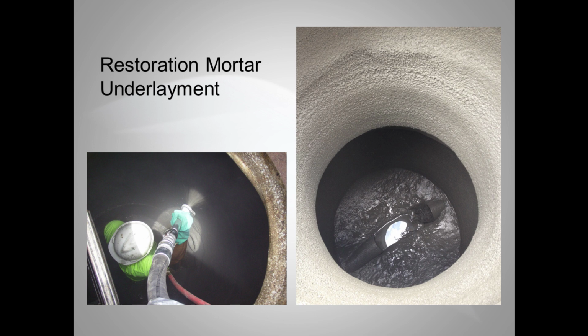Here you see a worker in the bottom left-hand corner. He's pneumatically applying microsilica restoration mortar. And this particular microsilica restoration mortar goes on anywhere from a ½ inch up to 2 or 3 inches thick, very low shrinkage, has a compressive strength of about 10,000 psi at 28 days. And it's just easy to mix and pump and spray. The structure on the right has actually been cement mortar lined using a centrifugal machine, and in this case the mortar is pumped to the centrifugal applicator and spun onto the surface. And if you look at the surface there, it's fairly smooth, but it has a dimpled surface that is really not suitable yet for the application of epoxy coating.